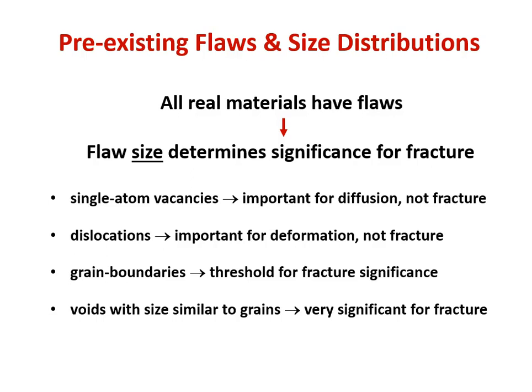Grain boundaries, those are defects that are just on the lower end of the threshold of significance for fracture. Voids with a size that are similar to your material grains. So a void, a crack, a defect in the material that's about the same diameter as your average grain size, those are the ones that are going to be very significant for fracture. That or obviously anything bigger. So there's your threshold for how small a flaw can be and still have a big effect on a material's fracture toughness, fracture resistance.